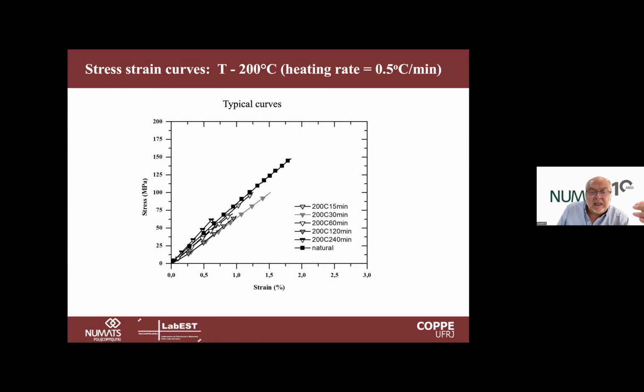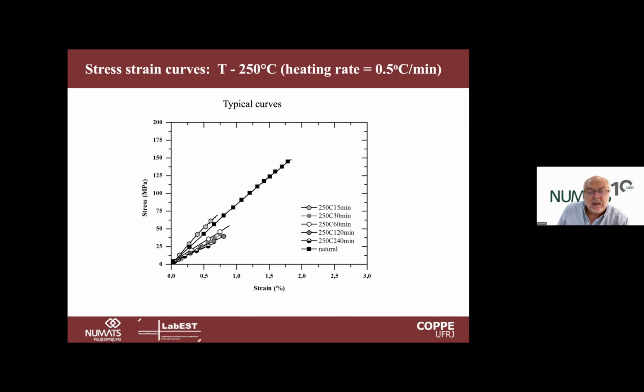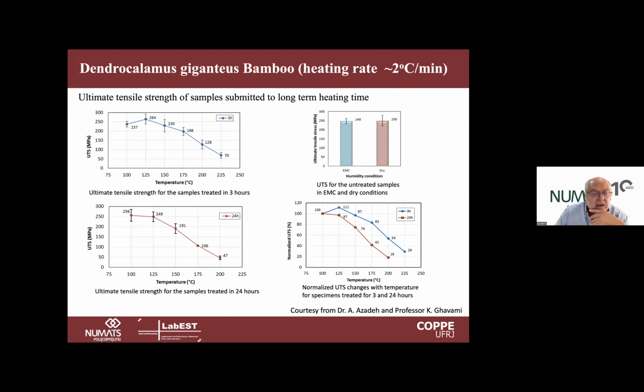Of course, when we go to 200, then the mass loss of the lignin and also of the cellulosic material starts to happen, and we have at 250 a strong decrease in strength and also strain capacity and elastic modulus. So we see here in these graphs that up to 100, 125, even 150, we keep very much the ultimate tensile strength, so it's nearly the same. But after 150, and mainly in the range of 200, 250, the reduction is quite expressive. When we normalize it, as we can see at the bottom of the last graph, we keep only about 20 to 30% of the strength, depending on the residence time.